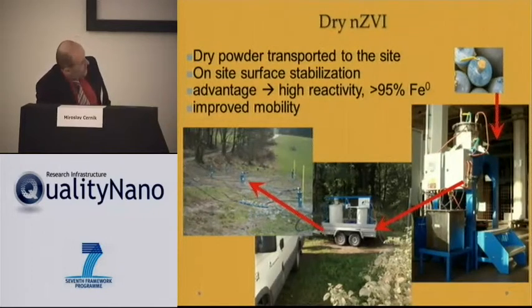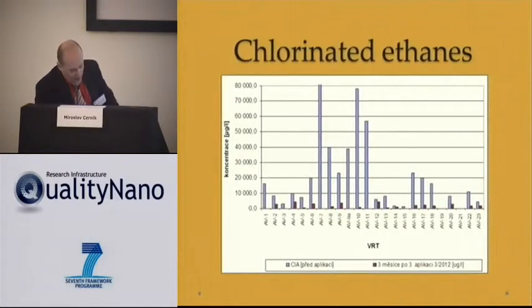Now first, how we do the application. We come with the powder particles. Then we do the dispersion on site, where we add some surface stabilizers to improve the particle migration, particle mobility, and then we apply some 1 or 2%, 2 grams per liter solution to the application well, and we do the monitoring.